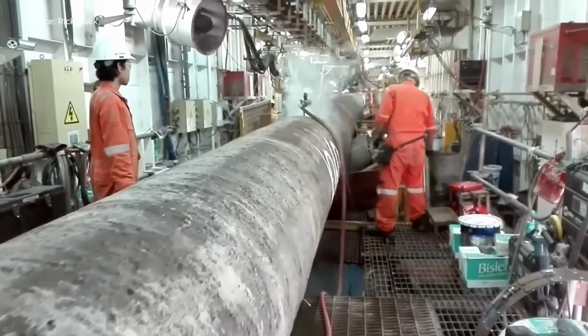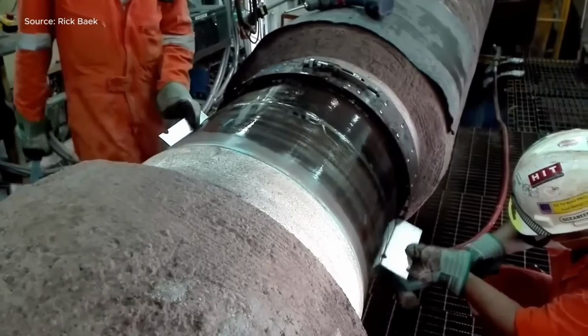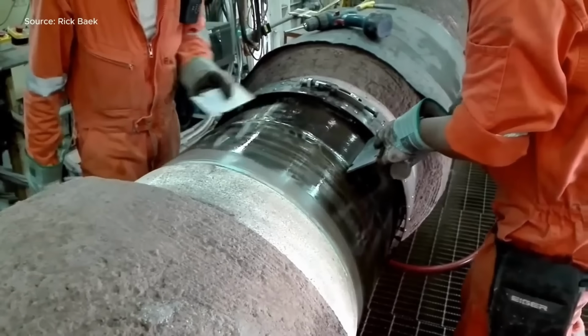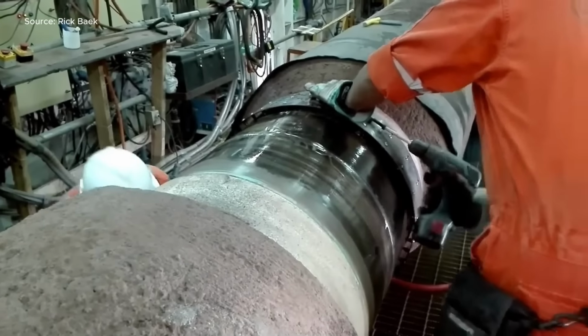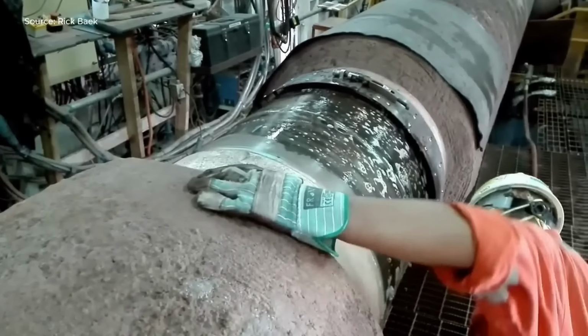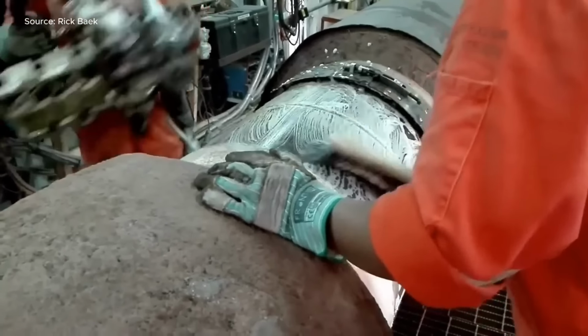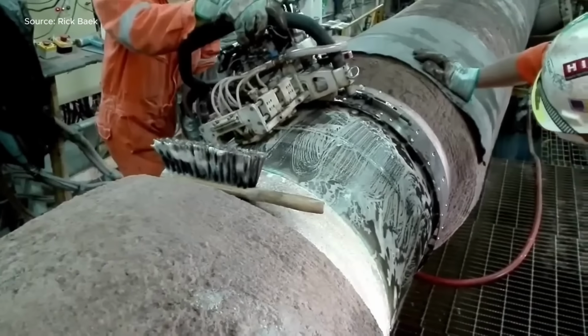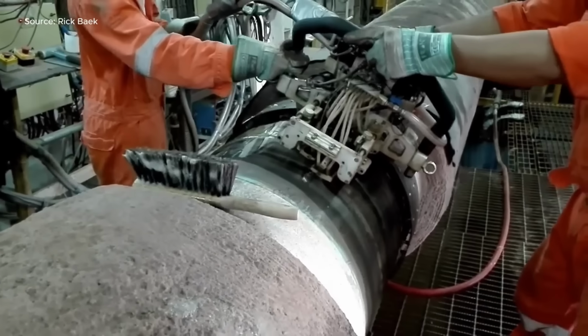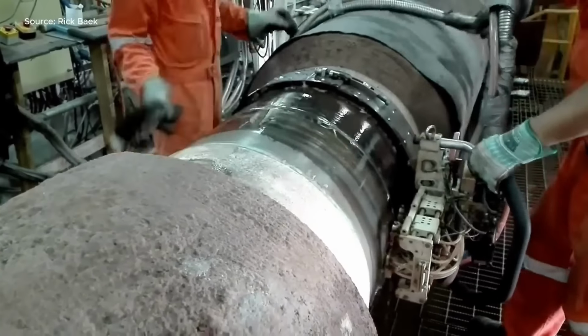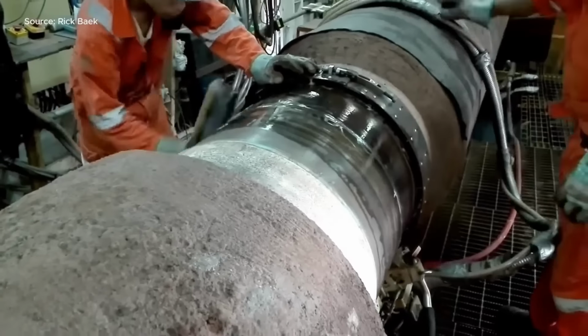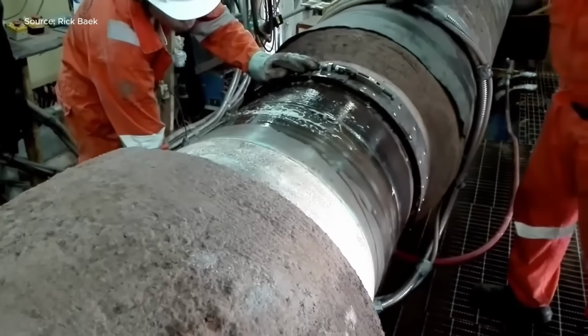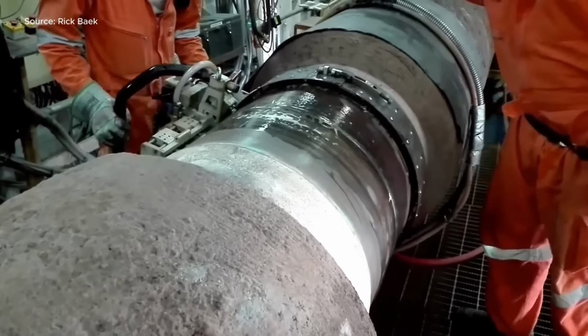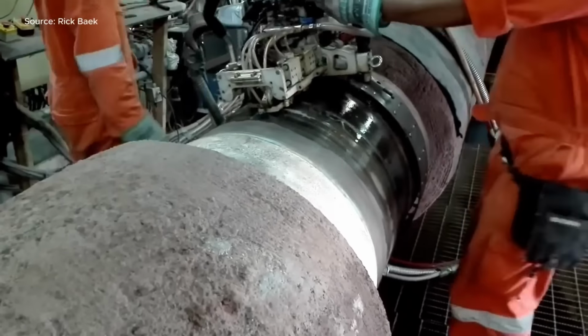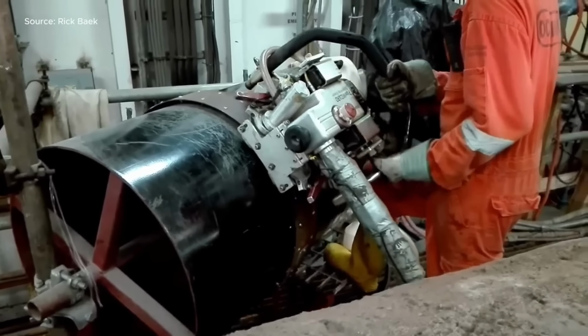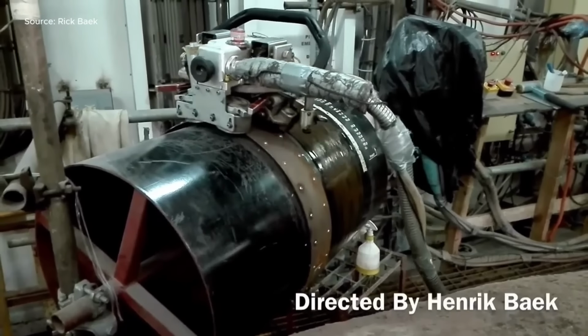Offshore pipeline construction typically takes place on a lay barge, where 18-meter pipe sections are welded and inspected before submersion. After welding, the weld area undergoes automated ultrasonic testing, AUT. A steel guide band is wrapped around the pipe to guide the scanner. The pipe surface is cleaned and sprayed with soapy water to reduce surface tension, allowing proper contact. The scanner circles the weld area, sending real-time data to a remote operator station for evaluation. Each scan cycle lasts about 3 minutes. Calibration ensures accuracy. Once verified, the weld is cleaned, insulated, and coated to protect against harsh marine environments before the pipe exits the barge into the sea.